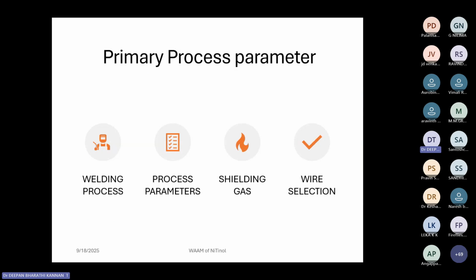In the fine tuning of wire arc additive manufacturing, we have to give importance to the process that we are going to use, because obviously it controls the deposition rate, as mentioned in the previous slide. And we have to give importance to process parameters like current, that is overall heat input, which is controlled by the current and voltage, as well as wire feed rate and welding speed. These have to be fine tuned properly so that we can control the metallurgical changes in a favorable manner. Another thing is that we have to choose the correct shielding gas. In some works people fully prefer argon-based shielding gases, and in some works people combine argon with oxygen to stabilize the arc. So there is scope for us to explore different shielding gas combinations, which will help in fine-tuning the properties of the wall that we are building.